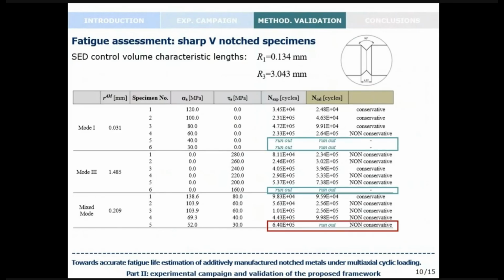And then, as you can see, at least for this case of sharp V-notch specimens, the methodology is able to capture the runout that we found experimentally, with the only exception of one case in mixed mode loading, in which the methodology provides a non-conservative estimation of a runout for a specimen that actually broke during the experimental